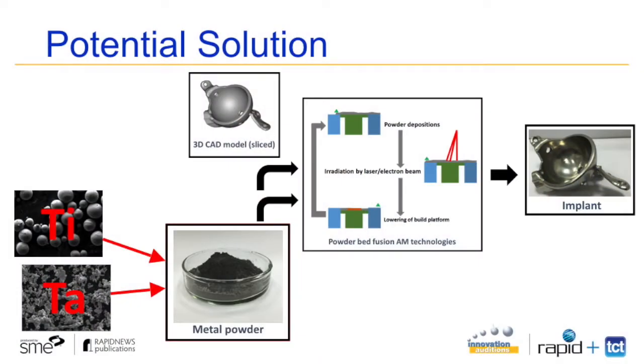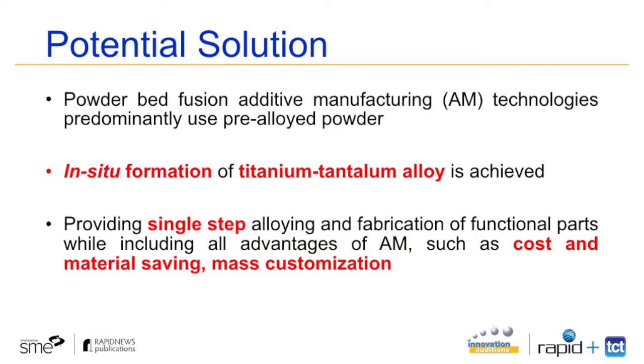So what we do is we use a powder mixture made up of titanium and tantalum, which are also popular for biomedical applications. And why are these different from other powder bed fusion technology? Because powder bed fusion technology predominantly uses pre-alloyed powders. That means within each powder particle itself, it is already pre-alloyed and consists of the composition that your material wants to be at the final part.